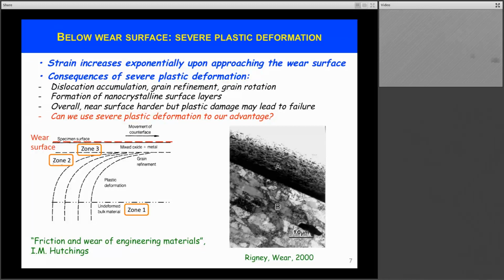At the wear surface, and this is what we see on the right-hand side, we may even observe the formation of nanocrystalline layers. This is the layer labeled A from the work of Rigney and co-workers. Overall, this plastic deformation increases the hardness of the wear surface, which is possibly useful, but at the same time it also reduces the amount of damage that the surface can take before it fails. And so usually, even though this hardening might be beneficial, after a while this region will break up and fall off, be ejected from the contact, and become wear debris.